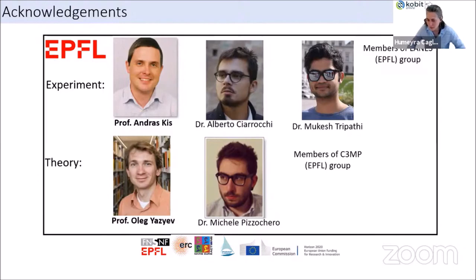Okay. And one last question from Laurence Boschier. He's asking, can you comment on the topological properties of the material? Yeah, so this is a good question. Based on the ARPES measurements, it looks like this material has type-2 Weyl properties, and it has Dirac cones. The issue with the way that we are doing the transport measurements is that these Dirac nodes are far away from the Fermi level, so we need to be able to dope it to access these topological parts of the platinum selenide.